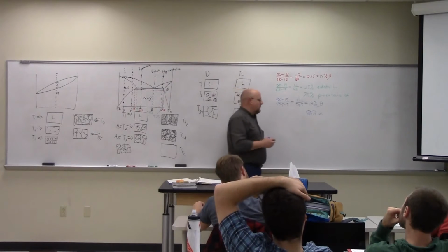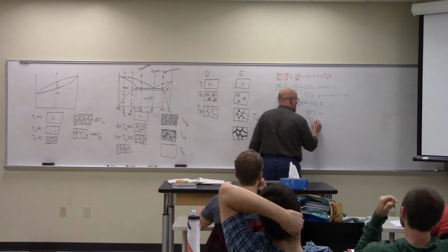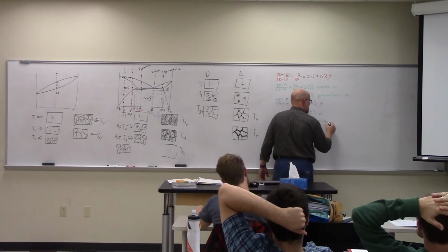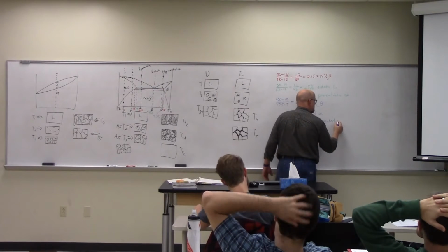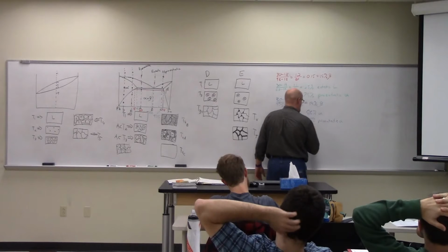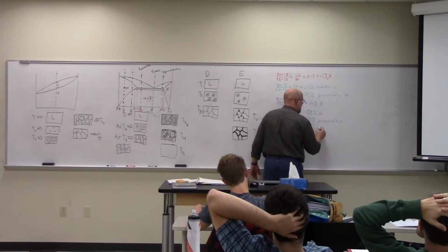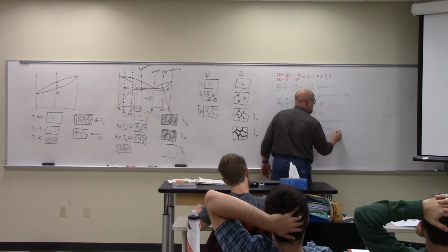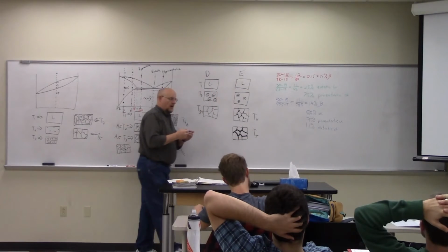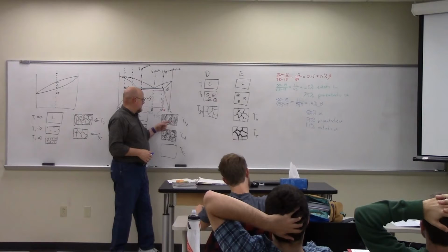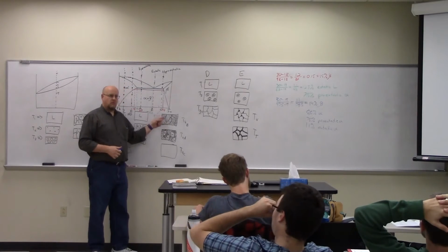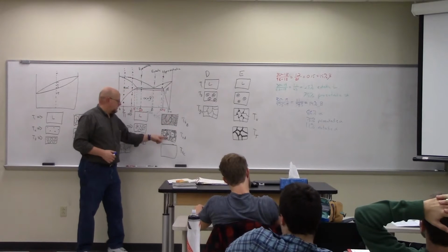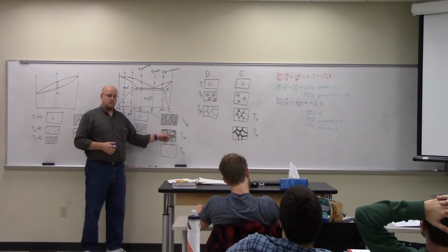But what I really have is 75% pro-eutectic alpha and 11% eutectic alpha. So 11% of my alpha is tied up in these striped characters, and 75% is tied up in these big chunks.